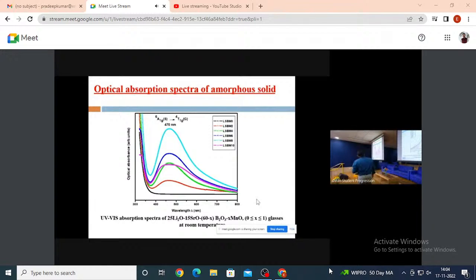So here the intensity of these peaks has increased with increasing the concentration of MnO up to 0.8 mole percent of MnO. Later, the intensity is found to decrease. But what is the reason? The increment in the intensity up to 0.8 mole percent of MnO shows that more octahedral Mn2+ ions exist up to 0.8 mole percent. Later, the Mn2+ ions decrease, and this may also be due to the decrement in the average distance of Mn2+ ions in the prepared glass sample up to 0.8 mole percent of MnO.